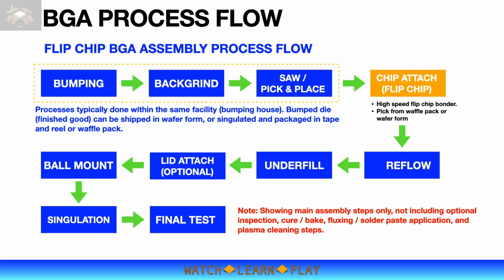After reflow, depending on the solder material used, the populated substrate may undergo a cleaning process in preparation for the next step, the underfill process. The underfill process uses epoxy resin, and it fills the gap between the bumps, die, and substrate. Once cured, the underfill provides solid mechanical support to both the die and bumps, preventing cracks on the solder joints and bridging the large gap in thermal expansion of silicon die and laminate substrate.